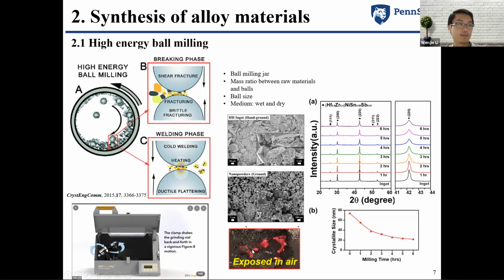It was by accident the first time that some nanoparticles dropped off and were exposed to the air when we loaded them into the graphite die for the SPS. Exposure to the air for just 1 or 2 seconds led to self-ignition of the particles, due to the oxidation of these nanoparticles, based on their very large surface areas.